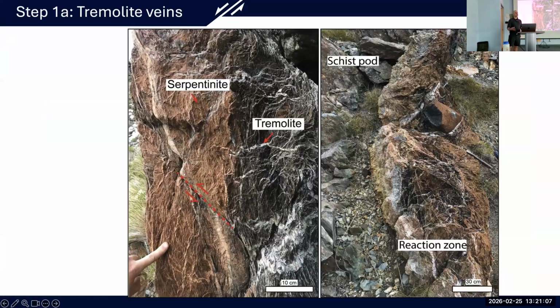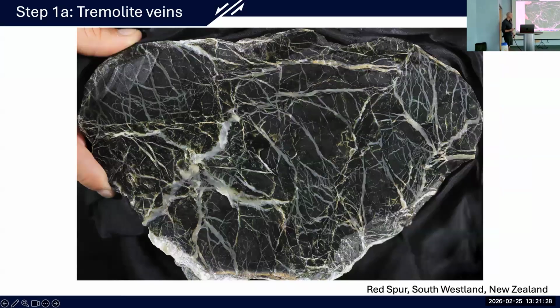And one of the first things that we see, if we look for the incipient formation of our nephrite, are intense zones of veins of tremolite running through the serpentine. This happens typically at the contact between the serpentine and that calcic siliceous rock. If we slice into this, we see really nice sharp boundaries between pieces of dark serpentine, where that pale greenish white is our tremolite, our nephritic tremolite.